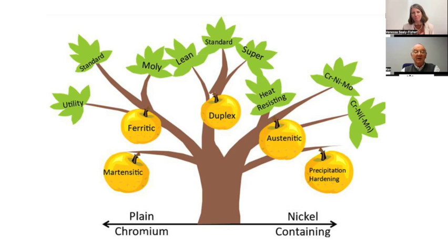Yes, absolutely. If we look at it, you can see on the lean side, it's leaning more towards the plain chromium side. What the term lean refers to is that it's lean in nickel. So the duplex structure, in other words, getting the austenite into a lean duplex stainless steel, is achieved by the use of manganese and nitrogen. Hence the term lean duplex. And its corrosion resistance is in line with that. The corrosion resistance is quite adequate for many, many applications, and they become useful materials.